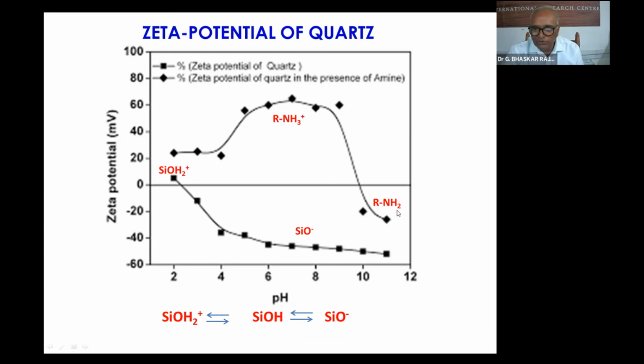It will be converted into amine, a simple primary amine. So there won't be any interaction with the SiO surface. As long as this is SiO, electrostatic attractions will take place, and you can create either a positively charged surface, or at this point neutralize the entire SiO. Suppose you want to work not in acidic conditions but in basic conditions, you can neutralize the SiO molecule by adding this RNH3 plus.